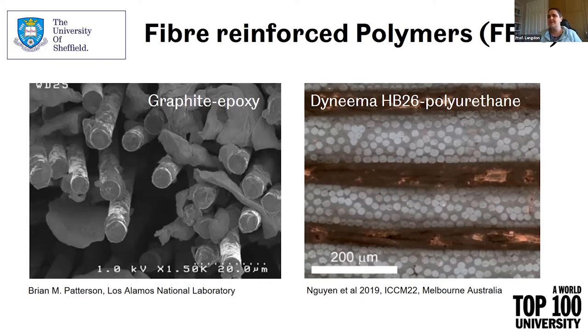If you have a look on the left-hand side of the screen, you can see graphite epoxy fibre-reinforced polymer, where the graphite fibres are magnified at a greater magnification than you see in the Dyneema to give you an idea of what they look like. The point of showing you this is that we tend to idealise these things, but in reality, they're not evenly spaced out and things are not quite as perfect as they are in our models.